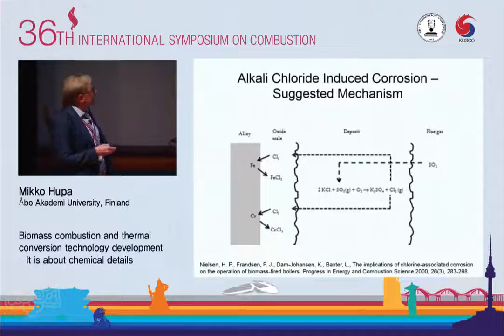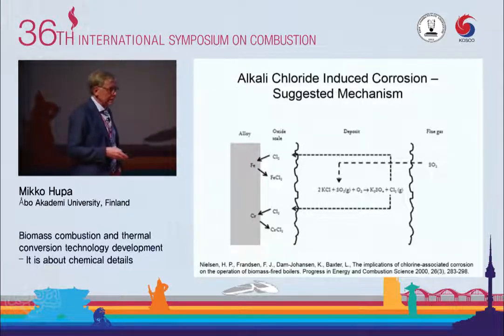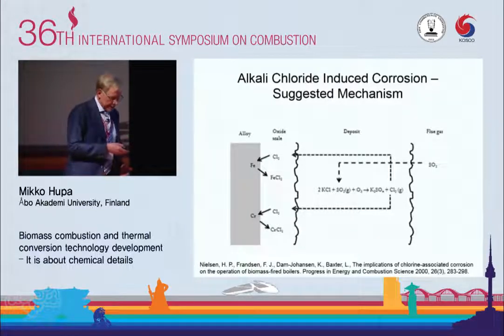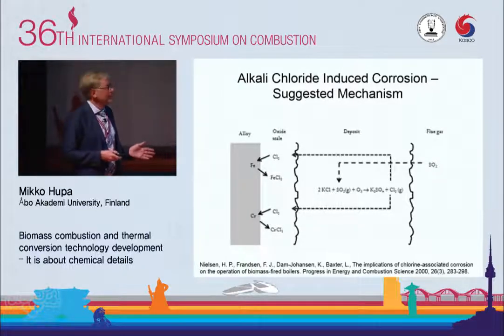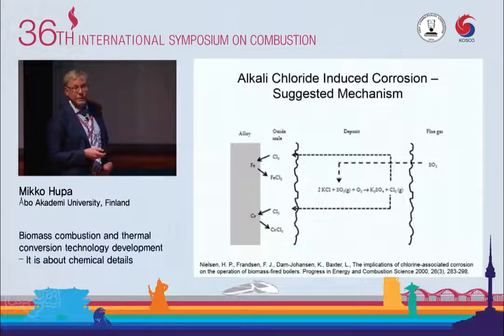So far, everybody agrees. Now, in this concept, the idea is that the chloride is activated in the deposit by reactions caused by sulfur dioxide from the flue gases. And the chloride is released as Cl2 gas. And that Cl2, chlorine gas, will react on the surface forming volatile iron and chromium chloride. This has been a difficult mechanism. Sometimes we have results which agree with this, but I will show you some results which do not agree. And you will see them here.